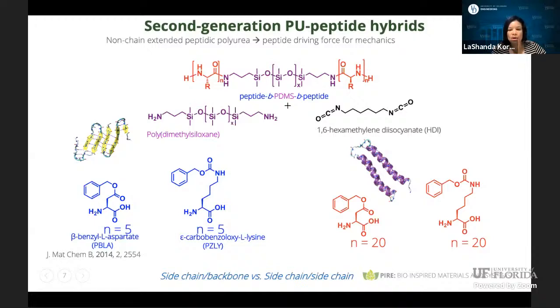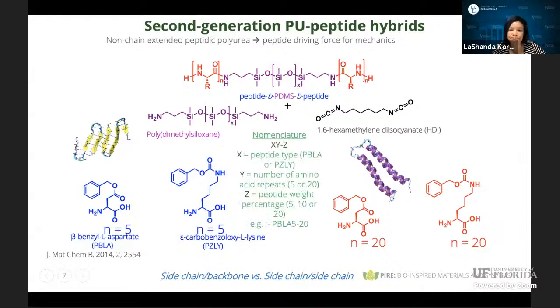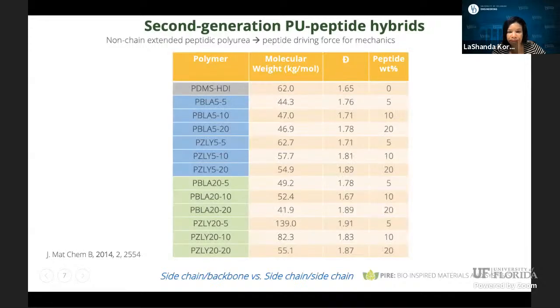In this case, we are also looking at two different block lengths. N equals 5, which should give you primarily beta sheets, and N equals 20, which should give you a mixture of alpha helical structures that can be modulated by the composition. So we varied our composition from 5, 10 to 20. And here the comparison is with PBLA, you have side chain backbone interactions. With lysine, you can have side chain interactions.